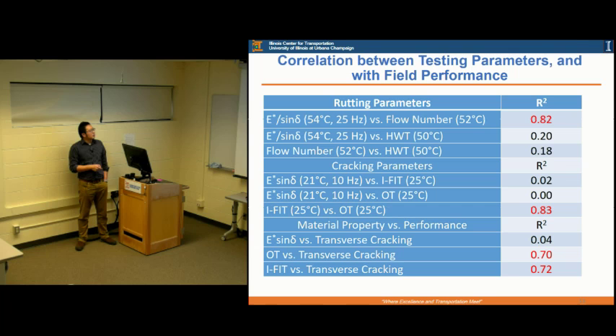When we put everything together, this is just a correlation for rutting parameters. We have a lot of rutting tests - flow number, Hamburg, and also E star over sine phase angle - and you see some trend, but not a very good correlation. Also, if you look at cracking parameters here, of course iFit is pretty good.